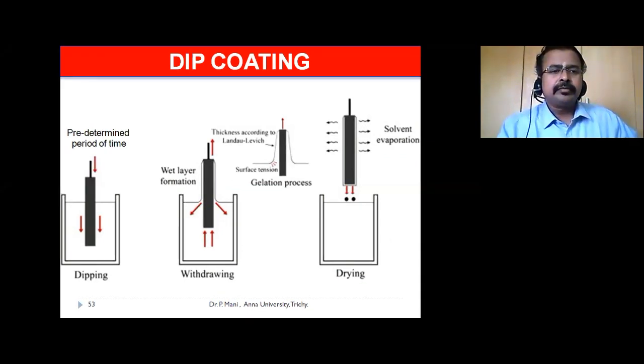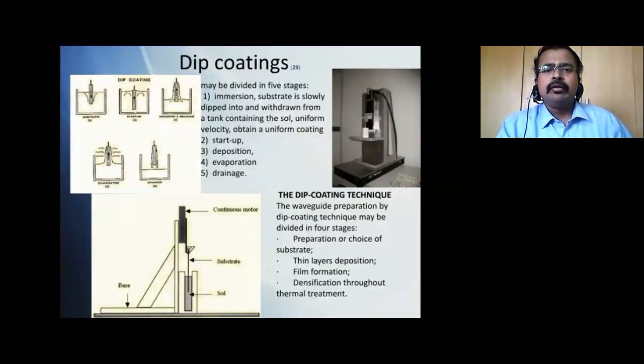In dip coating, we are immersing a clean glass plate in a beaker, which has the solution, for a predetermined period of time. After a particular time, we are withdrawing the glass plate. There is a formation of a wet layer, and then the solvent is evaporating. Then for a particular number of cycles, we can do the same process again and again, and we are getting very good coating of thin films.